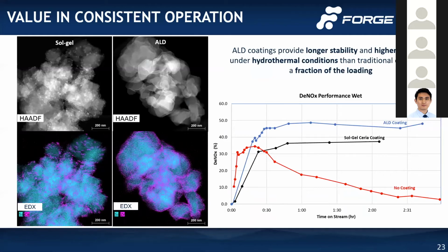I'm going to talk about the 3 different ways that we see ALD being useful for catalysis. One of them is overcoats, having an oxide deposited on top of your active catalyst material. The images on the left show a comparison of ceria deposited onto a catalyst, and this is zirconia deposited. It's not the same material, but the main point is that ALD will be uniform everywhere on the surface compared to sol gel, where you get some clumping. You can see a little more of that pink clumped around, not as uniform a deposition as you get with an ALD catalyst.